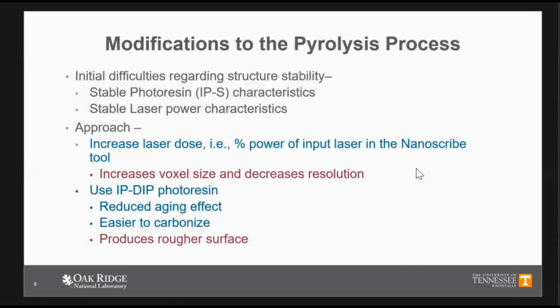So some of the modifications we have to make, because in our group we have established this recipe, and what we have seen is that if your IP-S photoresin is not stable or is close to aging, then you may have different results where your structures may be destroyed. Also, the laser power input of the Nanoscribe tool needs to be well calibrated to generate good structures. If you increase the laser dose, that will often give you better results after the pyrolysis. But the problem is that once you increase the input laser, your voxel size will increase, which results in less resolution in your structure.